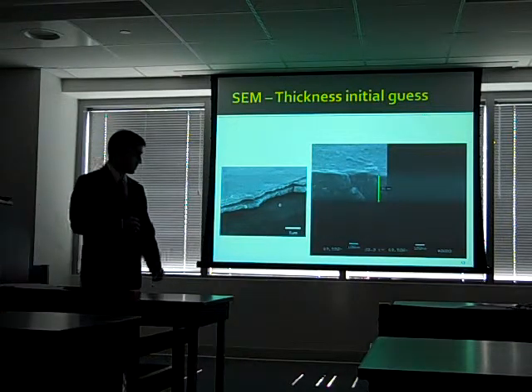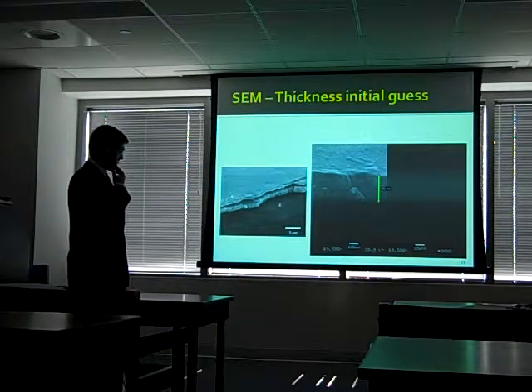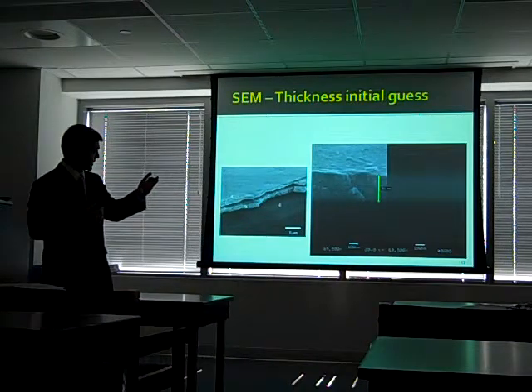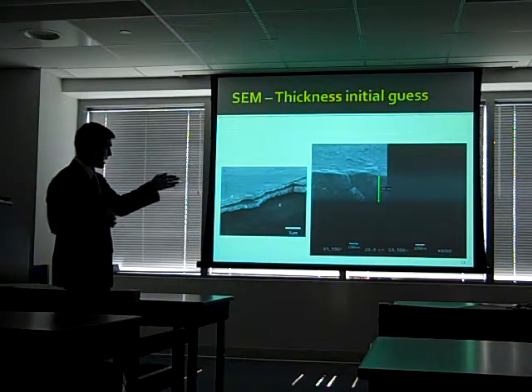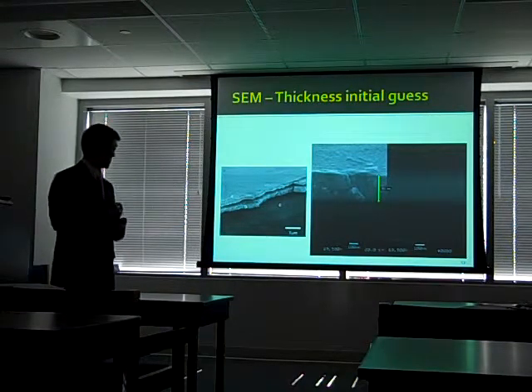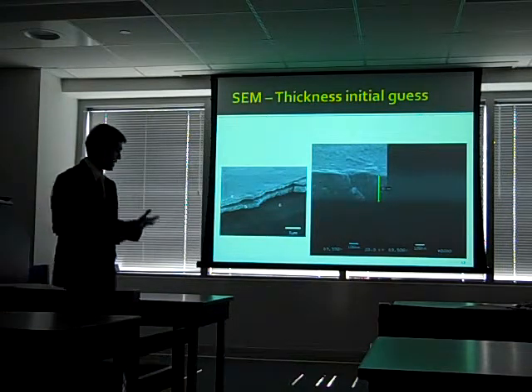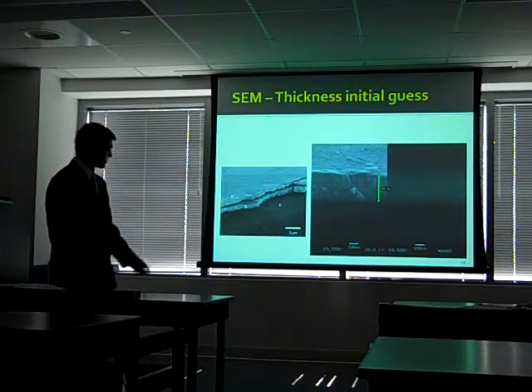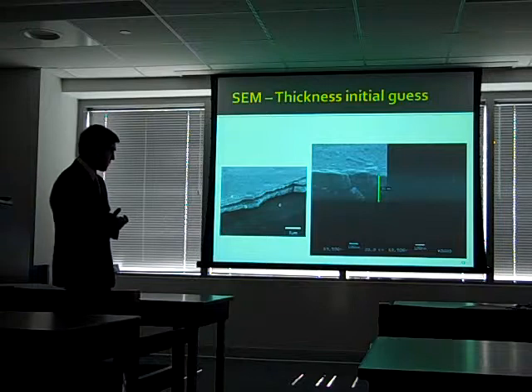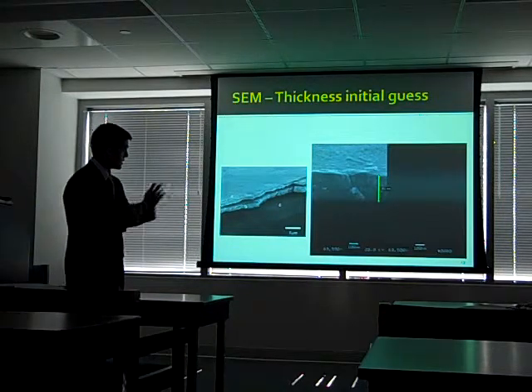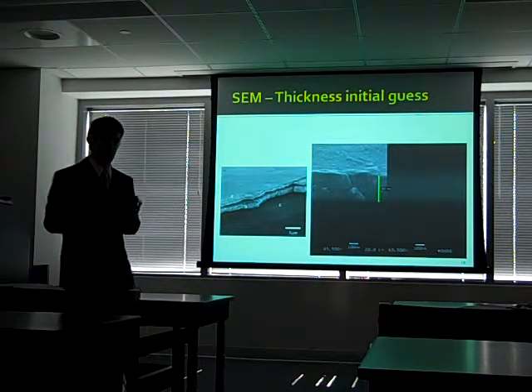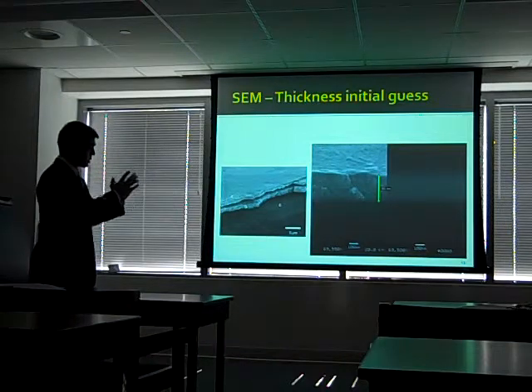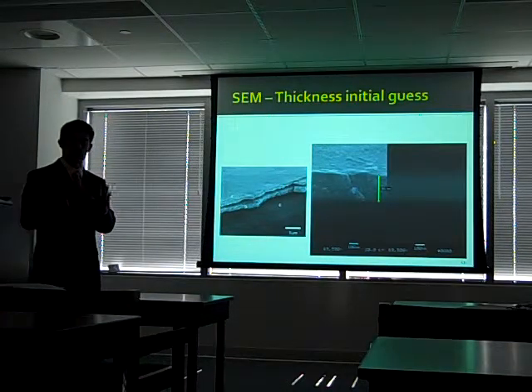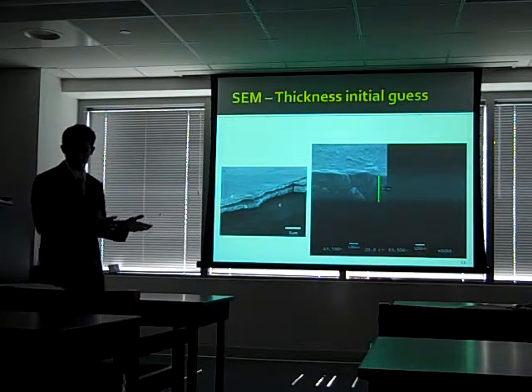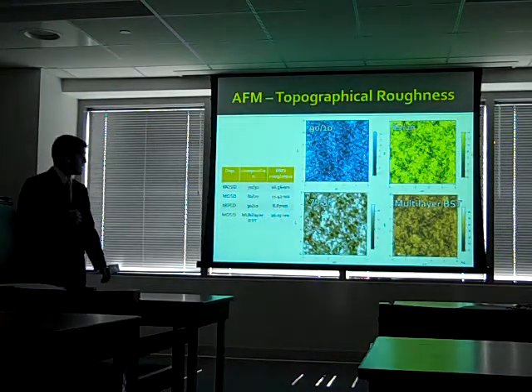I performed scanning electron microscopy on my samples, looking at the cross-section to get an idea of the thickness of the films, to provide an initial guess to the model and help develop it. It's really not the best way to measure thickness. The variation is about plus or minus 5%. So it wouldn't be used to accurately determine thickness, but it's sufficient to provide an initial guess to the model. So that's what it's used for.